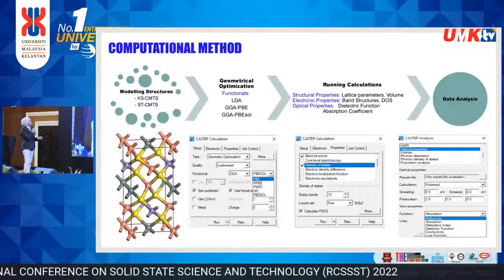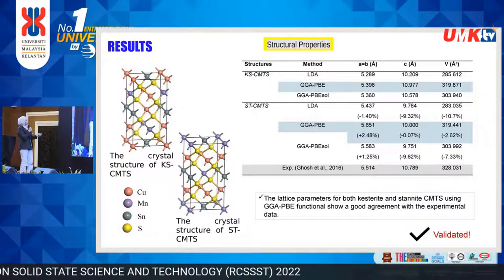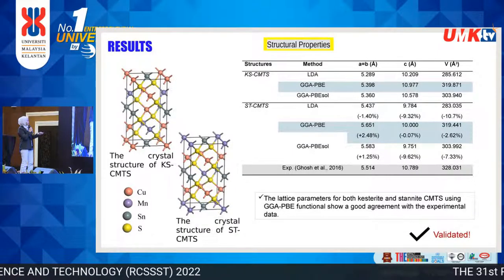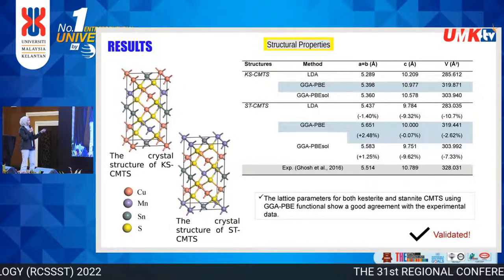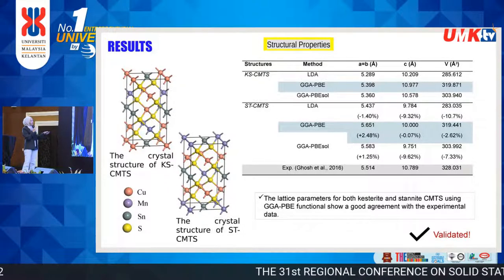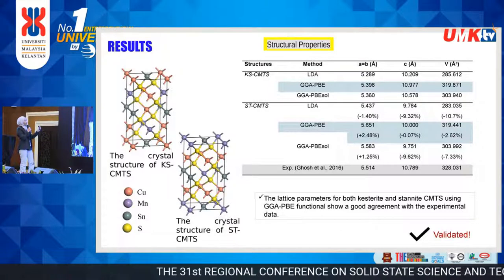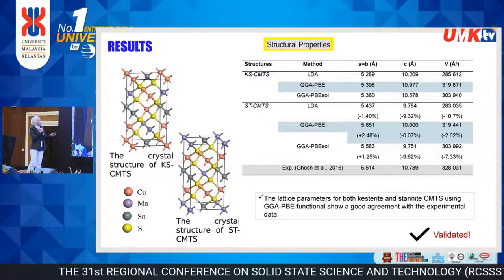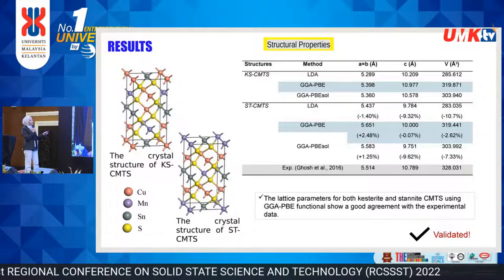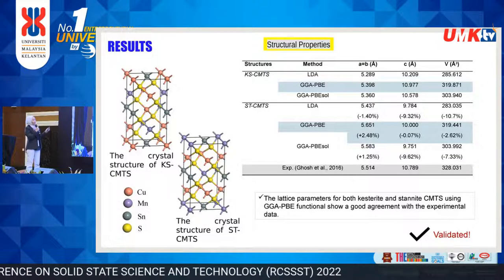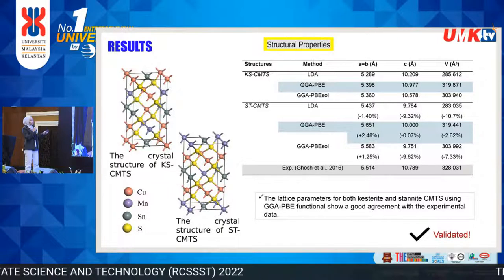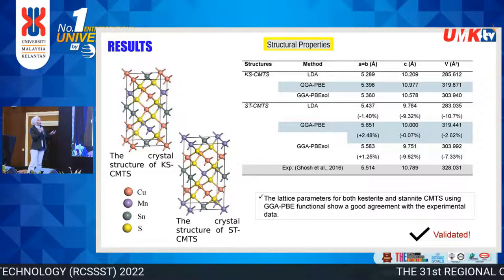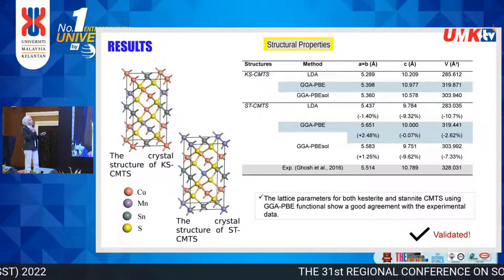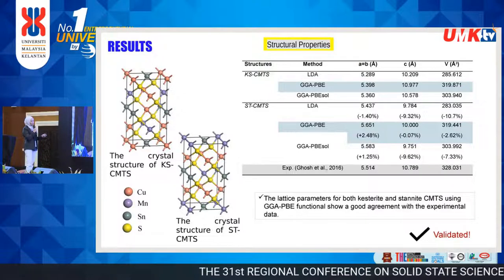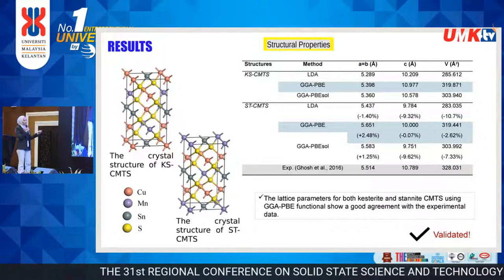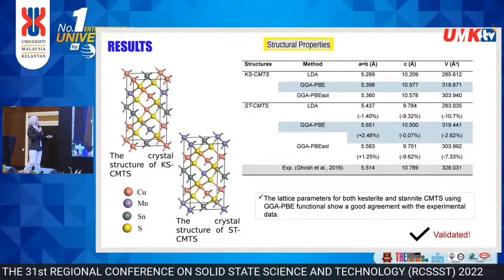Okay, this is the result for my material. This is the crystal structure for kesterite CMTS and stannite CMTS, which are not much different. And the lattice parameters for both kesterite and stannite CMTS using the GGA PBE functional show a good agreement with the experimental data compared to the LDA. So we can say that it is validated and verified against the experimental value.